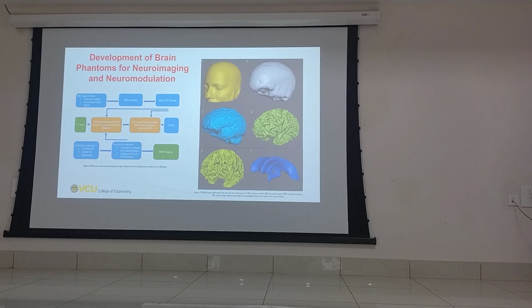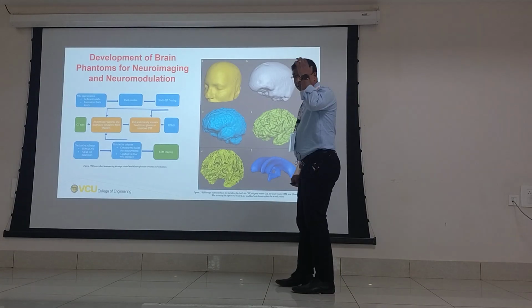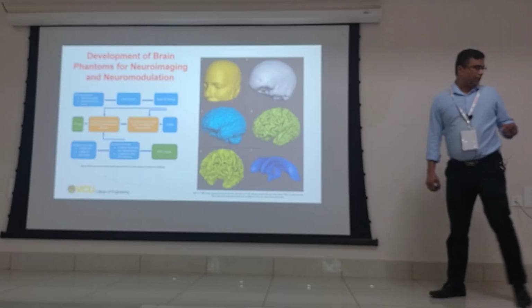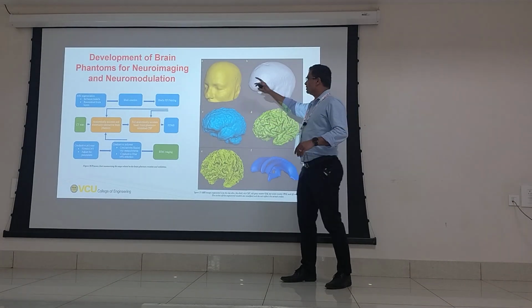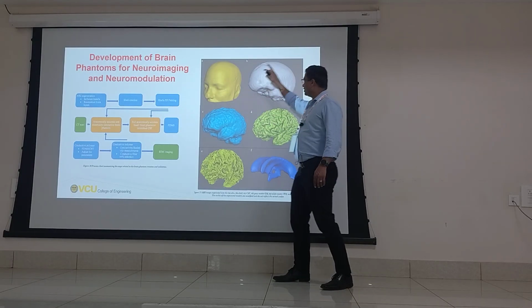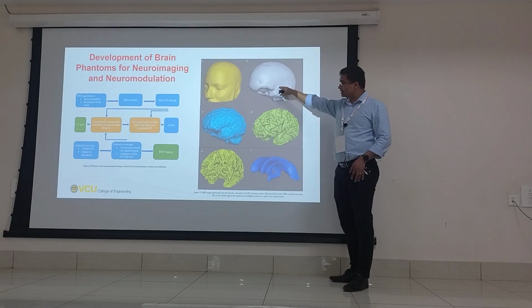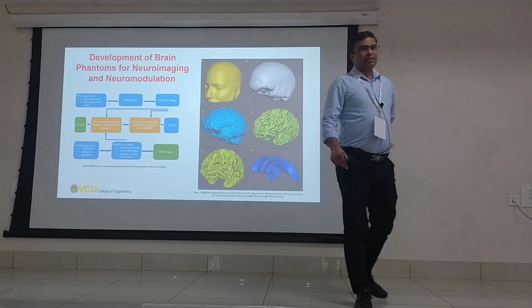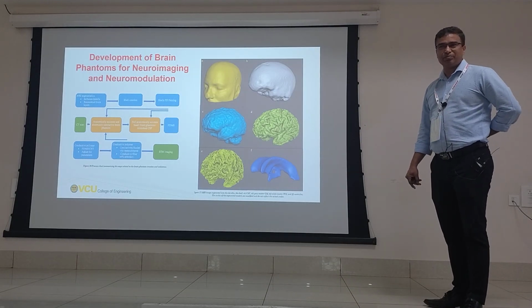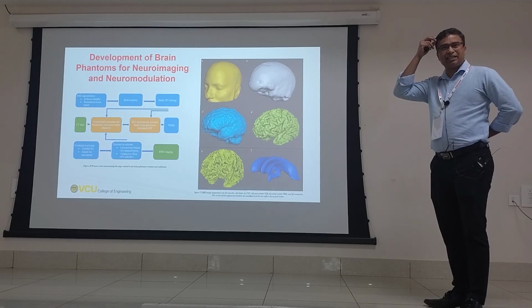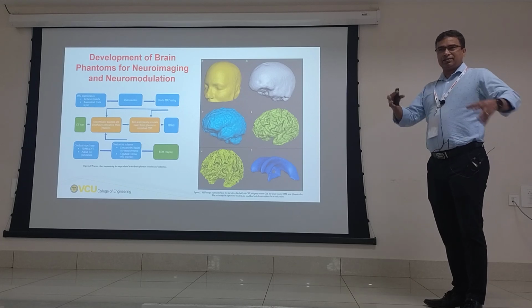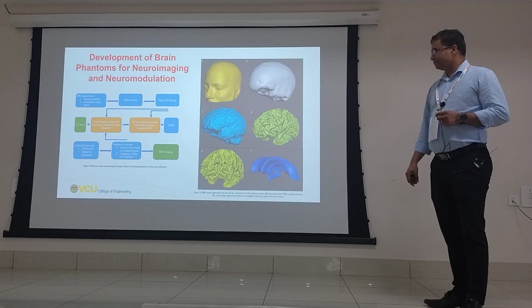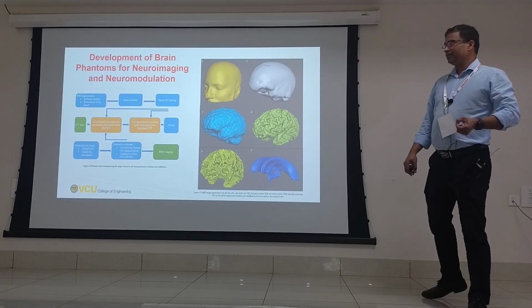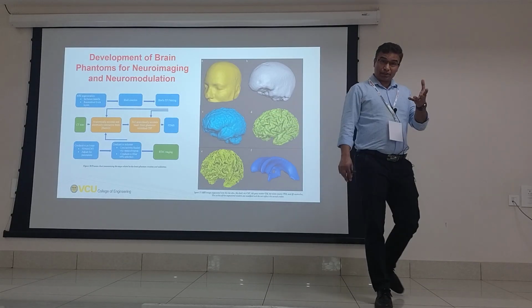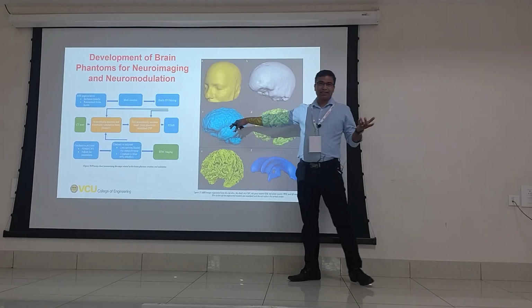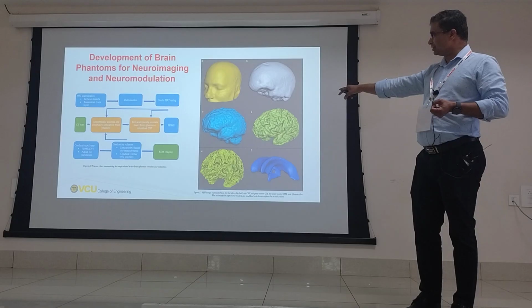And then, that's just replicating the structure, but now you want to replicate the conductivity of the brain layers. So the conductivity of skin is not that high, so you can ignore it, just create a PDMS, which is silicone polymer. Skull is similar to ABS plastic, so we use that. CSF, what is the best material to replace CSF? Cerebrospinal fluid. It's a transparent, odorless fluid in your head that protects the brain. Saline solution. Yeah, if it's saline, its conductivity is also high. So we basically made a saline solution with the matching electrical conductivity of CSF.